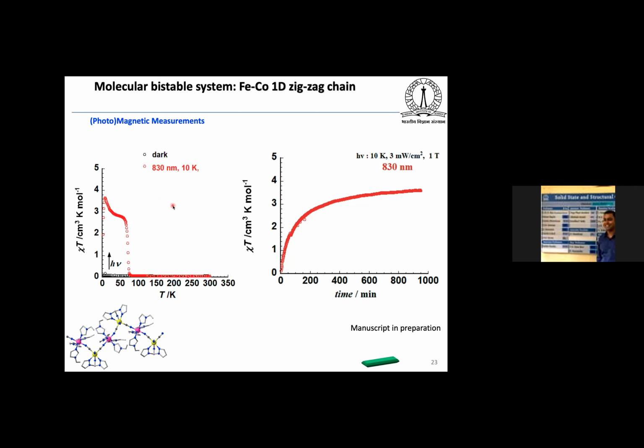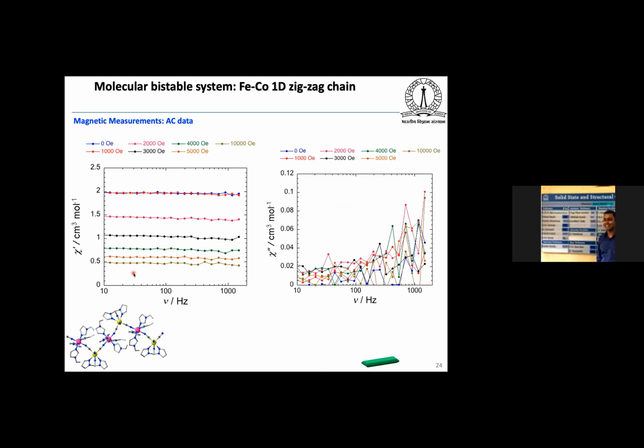And then we have studied the magnetic property of the photo-induced metastable state, and you can see there is a small increase that is coming from the ferromagnetic interaction between the two different chains, and the metamagnetic state relaxes back roughly around 80 Kelvin. That matches very well with the data available from the optical reflectivity measurements. So you can see here the paramagnetic high spin state relaxes back to the diamagnetic ground state at roughly around 80 Kelvin. Then we studied the AC magnetic measurement of the photo-induced metastable state using an external DC magnetic field from 0 to 5000 Oe, but unfortunately we have not observed any slow relaxation of the magnetization in this experimental range.